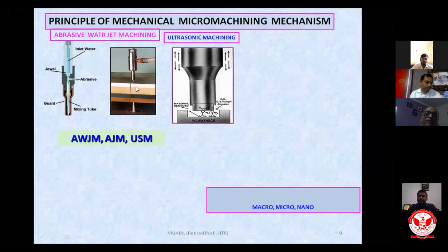Now, one thing I would like to tell here, in case of abrasive water jet machining, the velocity with which this jet is moving is very, very high. It can be as high as 900 meters per second. So you can calculate the kinetic energy of the abrasive particle with which it is hitting the workpiece surface over here, and that kinetic energy is responsible for removing the material in this particular case.